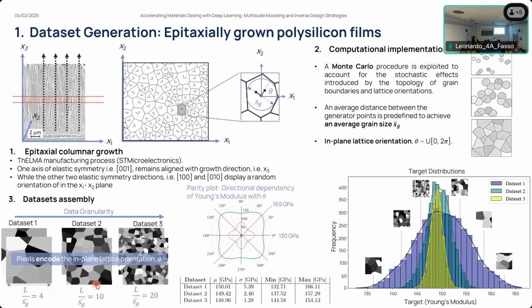With the microstructures, then we can move on and perform numerical homogenization in order to extract the target value that is going to be the objective for our SP relationships, which we will extract with the convolutional neural network. Specifically, the target is in terms of the Young modulus along the first axis of the global reference frame. We can observe here the histogram with the target distribution, where we see that all of the data sets have virtually the same mean value, but what varies significantly is the level of dispersion around the mean value for the different data sets, which is consistent with the fact that as we go with smaller stochastic volume elements, we will have a larger scattering of the mechanical properties when performing homogenization.